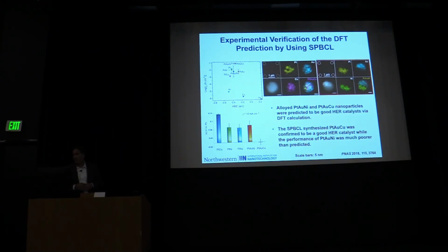Well, we can make all those particles, and we did. And then we studied them, and we look at them and compare them to platinum. So this is the overpotential, and you can see platinum copper here, lousy, platinum nickel, lousy, platinum gold, lousy. Here's one of them, lousy. That was a shocker. Then you look at this guy, platinum gold copper.